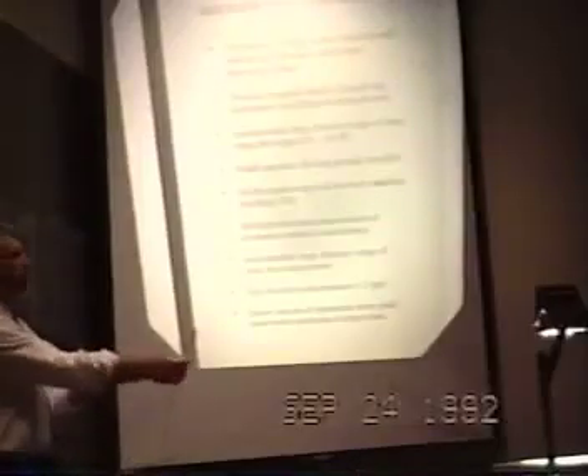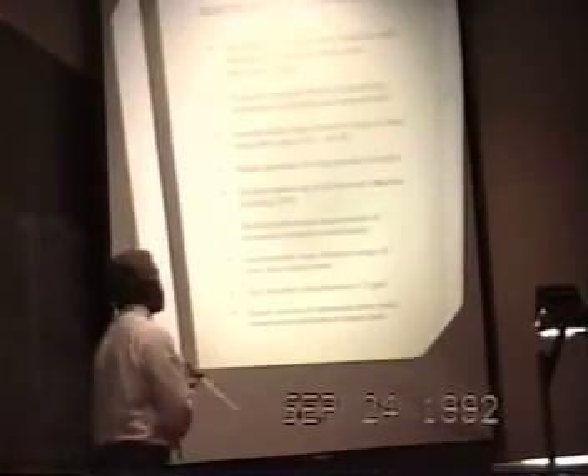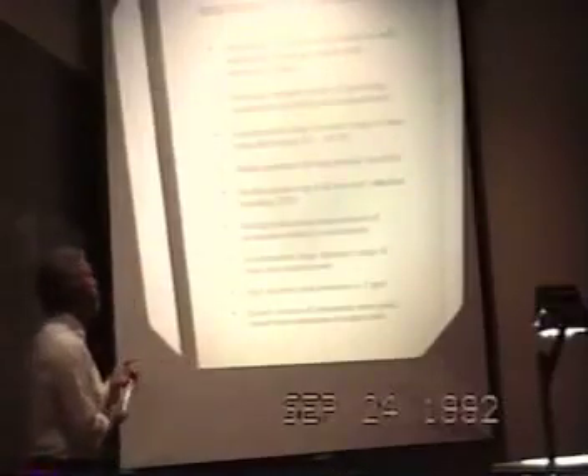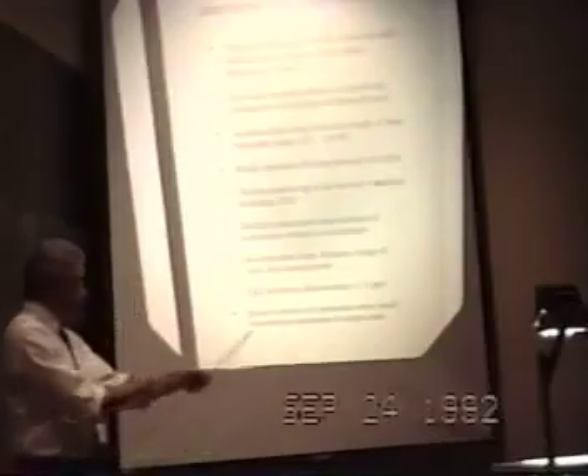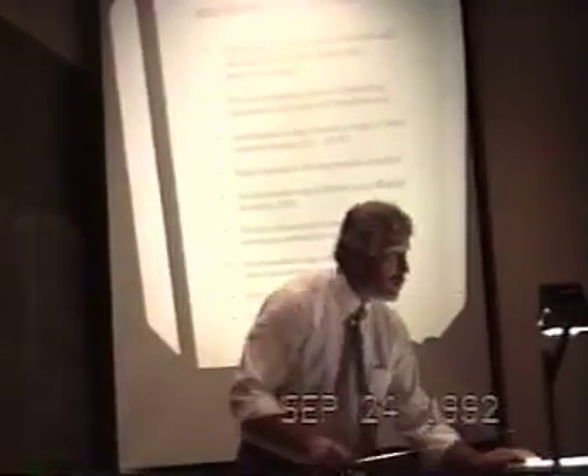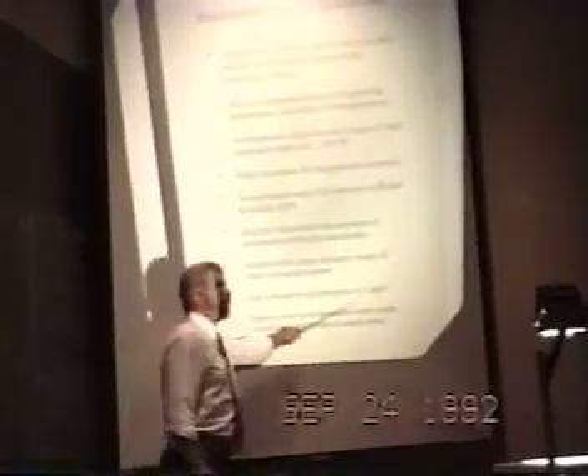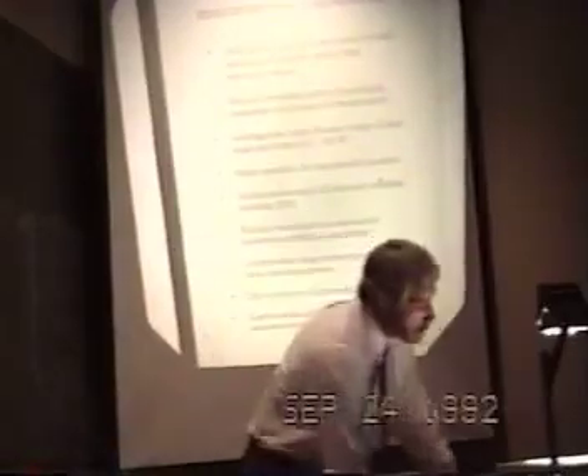producing this effect. We wanted to make multiply redundant measurements of the parameters critical to the calorimetry, in particular of the temperature. We wanted to accommodate a large dynamic range, and we wanted to maintain the accuracy and precision, particularly the accuracy of the measurements, at better than 1 part per thousand. As I said before, we wanted to make the known sources of systematic error yield conservative estimates of the output heat.